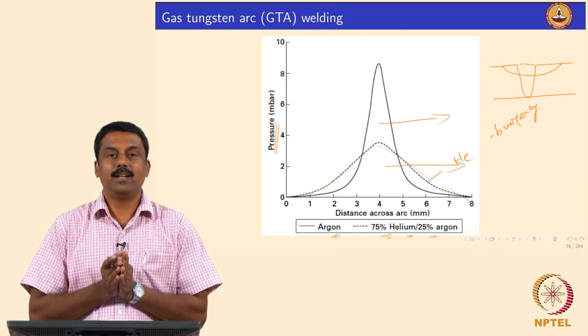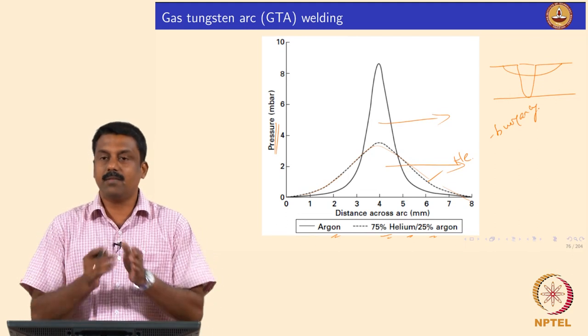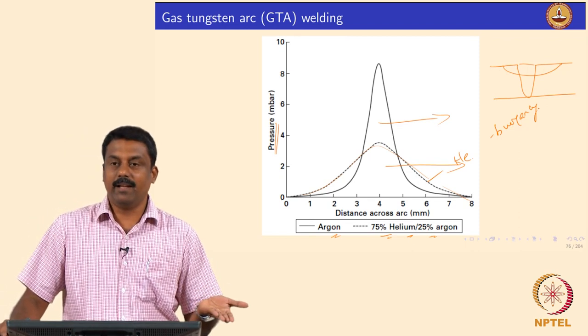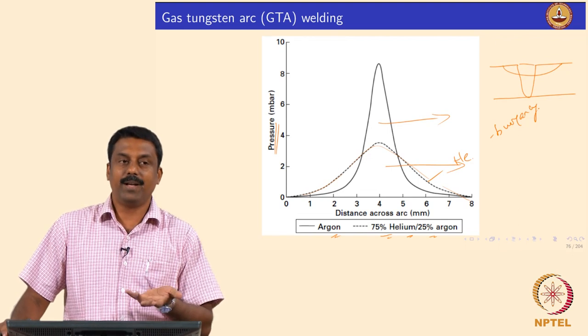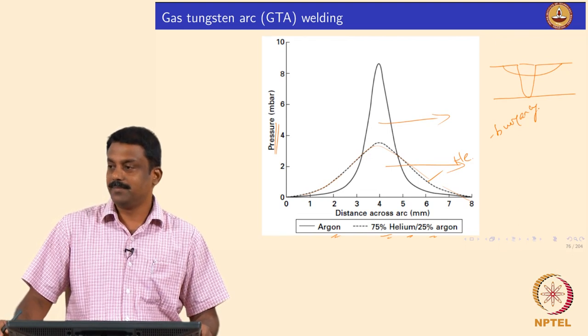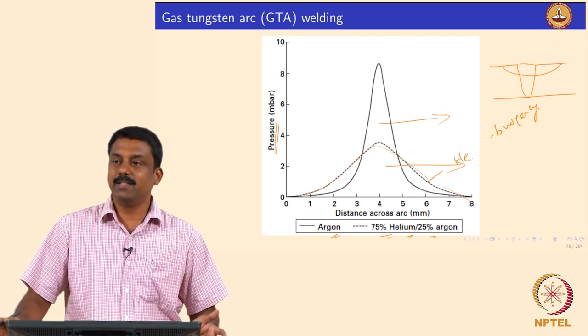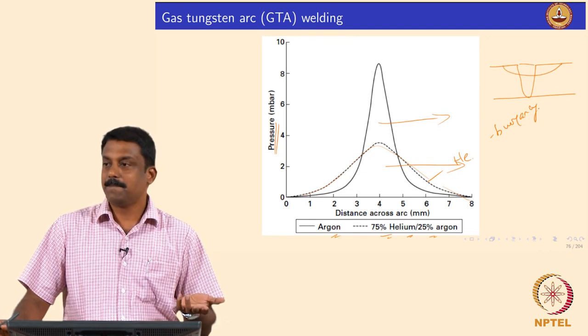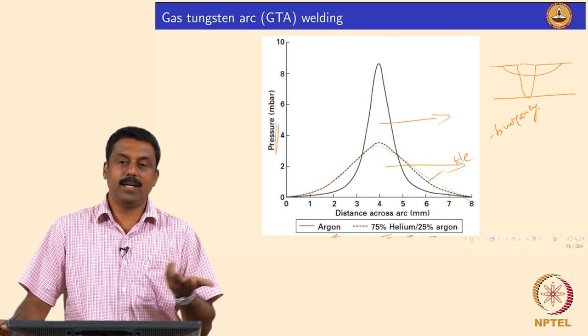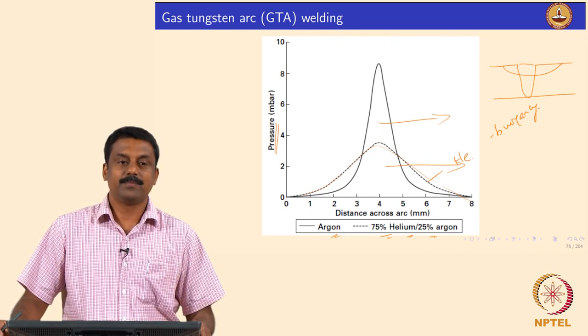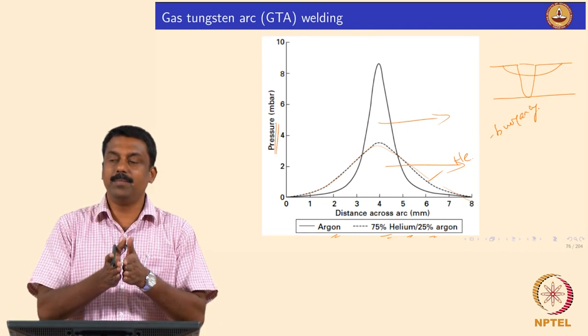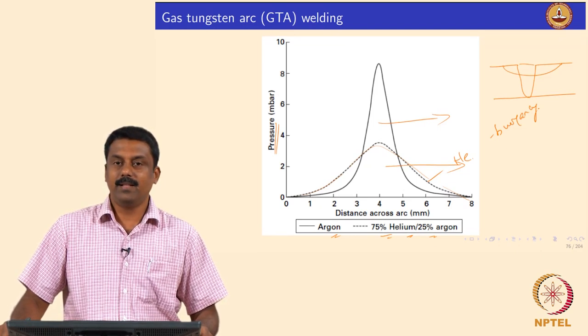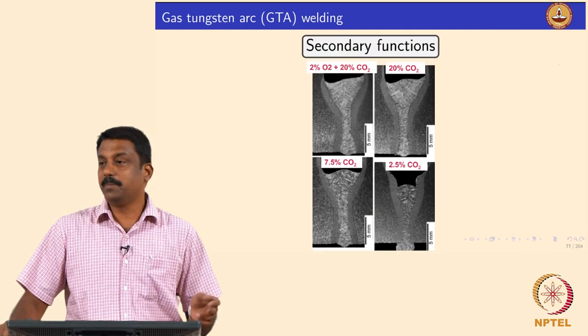So you can clearly see that just by changing the shielding gas you change the weld geometry. If you use argon, heat concentrates at the core of the arc, leading to deeper, narrower penetration. Change it to helium — which is a convective gas — or add argon-CO2, and you see the effect. Carbon dioxide is also effective in heat transfer because of dissociation, and helium or hydrogen is effective because of convective flow. We have done experiments to verify that.